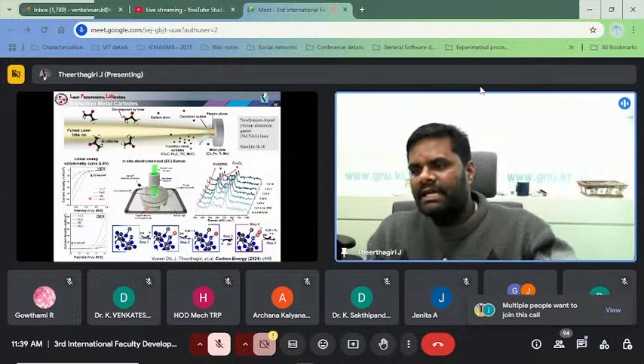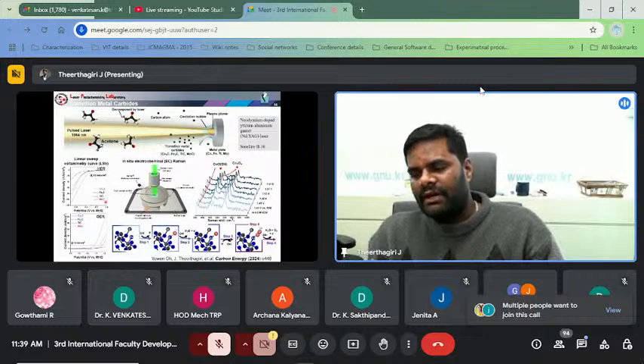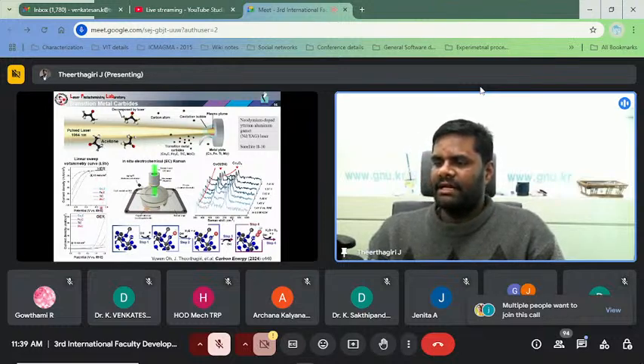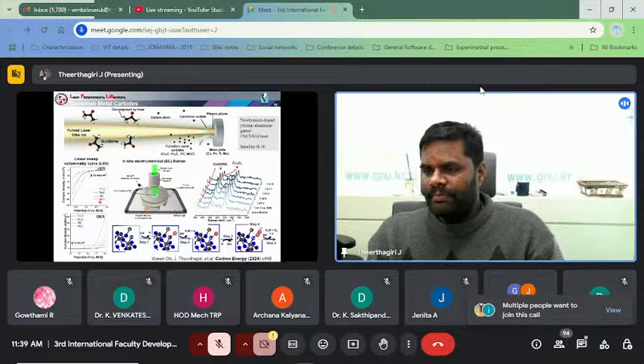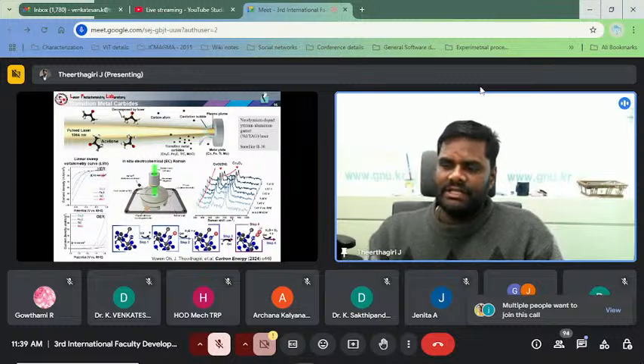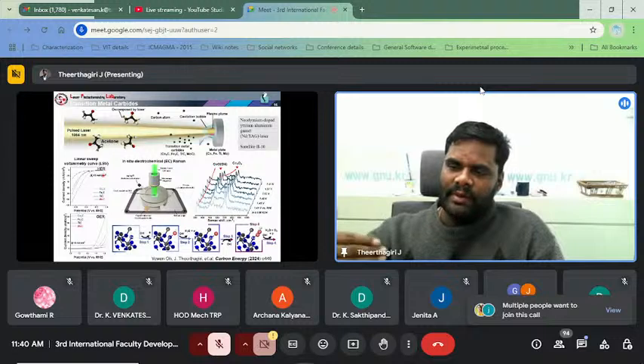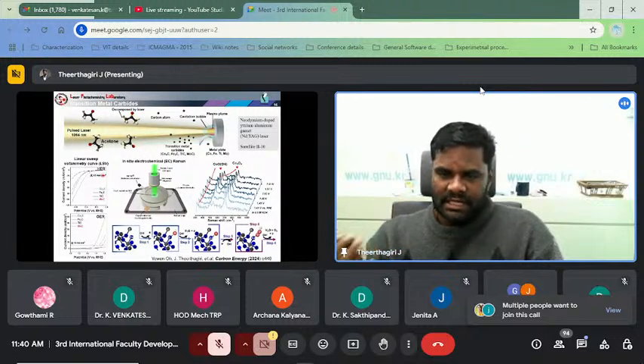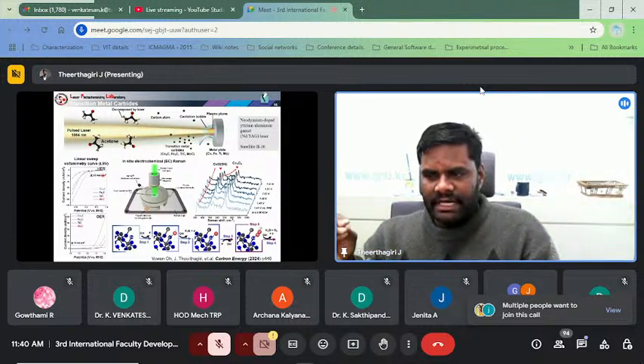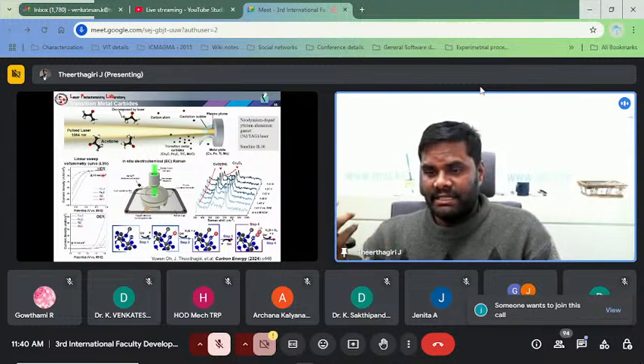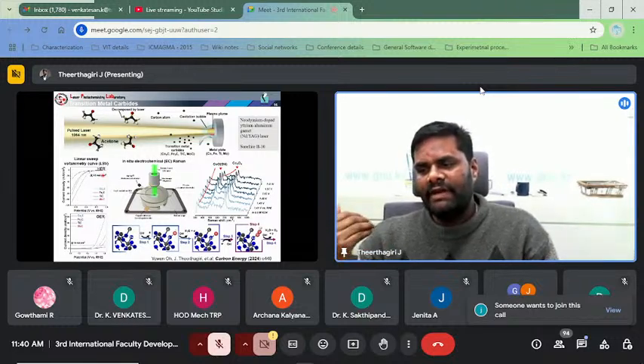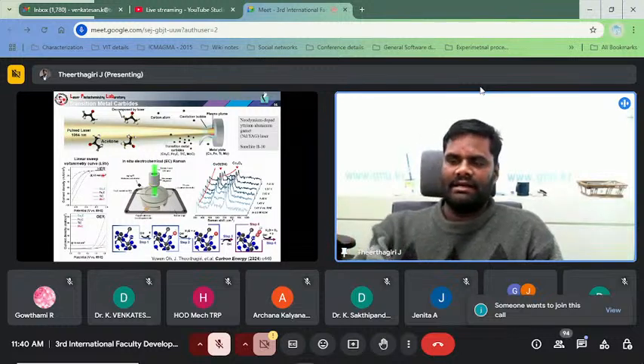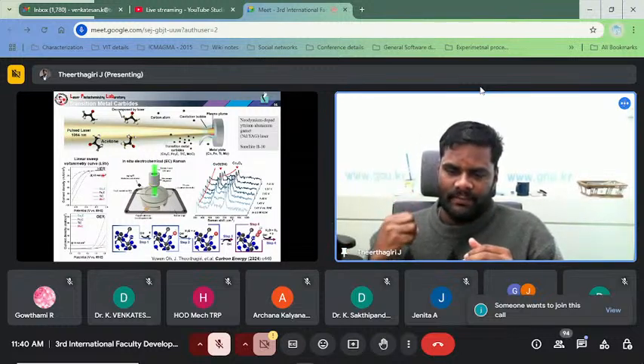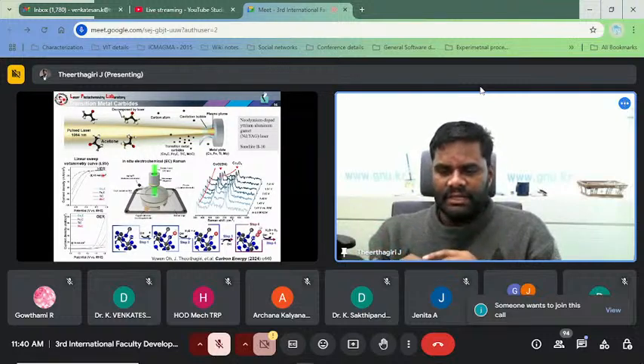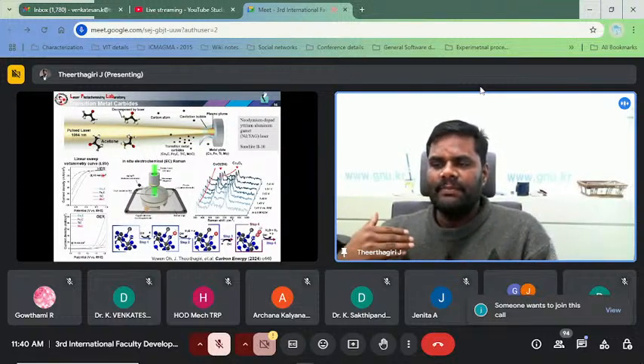Okay, we applied them for the HER and OER. There are various materials I studied here, and only molybdenum carbide is the best for the HER. Why is molybdenum carbide the best for HER? That is the science behind it. It has more d vacancies. When the d band vacancies are much higher, it is easy to bind with the hydrogen atom.